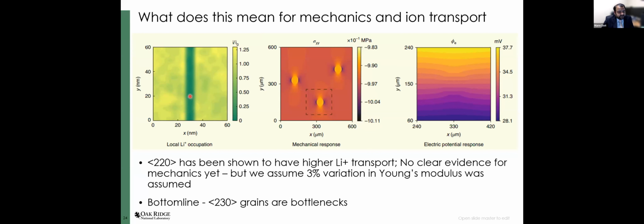So essentially what this means in a real system is if you have a 230 space group within a 220 matrix, that 230 space group acts as an ion blocker, and ions have to move across and around it in order to transport, and that acts as a potential barrier and a hotspot for bad stuff to happen within the electrolyte. At the mesoscale, in a 600 micron kind of domain, we see that these secondary domains with effectively different mechanical properties act as a concentrator for stress. It also acts as a concentrator for potential when you apply a field through these